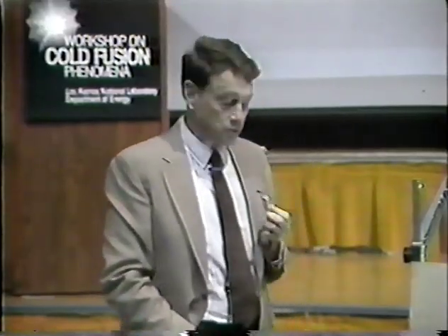The first indication, of course, is that we have reproduced the implantation conditions of about a decade ago, when very detailed profiling measurements did indicate that when you implant to saturation at such temperatures, you achieve an atom ratio of 1.3 deuterons per palladium.